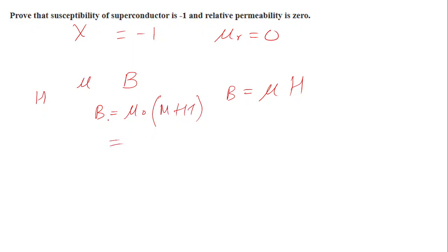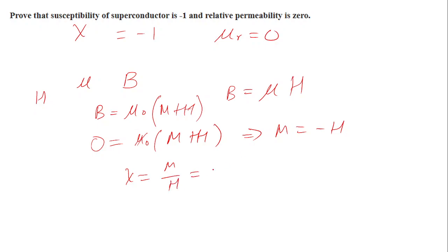So this is one relation, and we know that a type 1 superconductor, in the perfect superconducting state rather than the mixed state, is a diamagnetic material. That means no magnetic flux density is inside the superconductor. So we can set B to 0, and then this will become 0. So M is equal to minus H. Now we know chi is M by H, and M is minus H. That means -1.